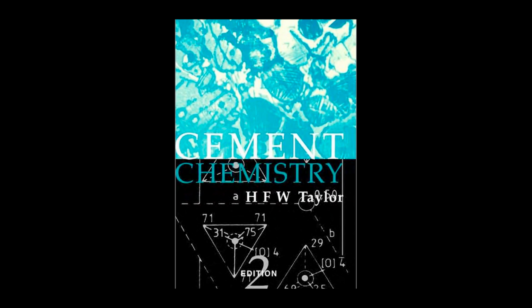But I understand that this conversion from AFT to AFM isn't always guaranteed, especially in real-world scenarios. That's a great point. Even a small amount of atmospheric carbon dioxide, which dissolves in the pore solution, can stabilize the ettringite, preventing its conversion to monosulfate. And this means that in many field concretes, ettringite can persist indefinitely, which is critical for understanding later durability issues like delayed ettringite formation.